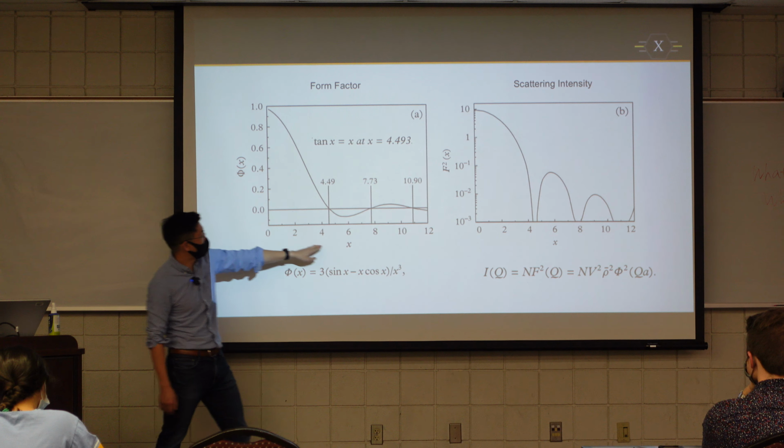If you look at this equation, when X goes up, because X cubic is at the bottom of your equation, so when X is closer to infinitely large, the top will be very small compared to the X cubic. So scattering will always diminish in intensity at high Q. That is why, if you look at normalized intensity, at low Q it is 1 and here it is almost 10 to the minus 5. So that's little signal. Okay?